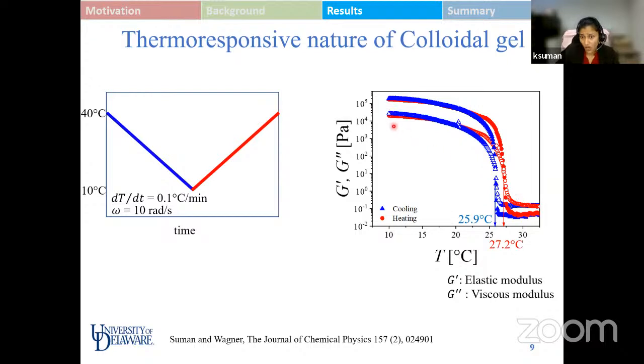On further reheating the sample, it follows the same path for some time and then undergoes an intersection at a different temperature as opposed to the cooling cycle, and again saturates to a very low value, which suggests that it is thermoreversible in nature. Now the intersection of G prime and G double prime is also used to characterize the gel point temperature for this specific system in the literature.